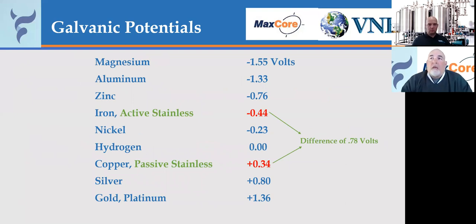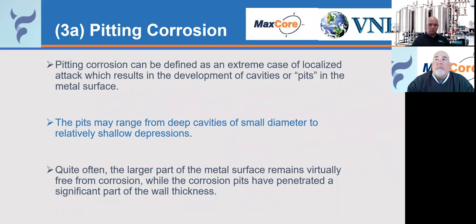Now, when we're talking about galvanic potentials, this is the chart showing the galvanic differential between active stainless steel and passive stainless steel. So if you notice, active stainless steel gives off a negative 0.44 volts of electricity, whereas the passive stainless steel gives off a positive 0.34 volts. That's a differential of 0.78 volts between active stainless steel and passive stainless steel. So that's your differential that's taking place whenever you have those in the same plane. Pitting corrosion can be defined as an extreme case of localized attack, which can result in deep cavities and pits on the surface of the steel. They can range anywhere from a very small diameter to very, very deep pits within the surface. And quite often, the larger part of the metal surface remains unchanged. It's just in a specific area where you might have this corrosion taking place.